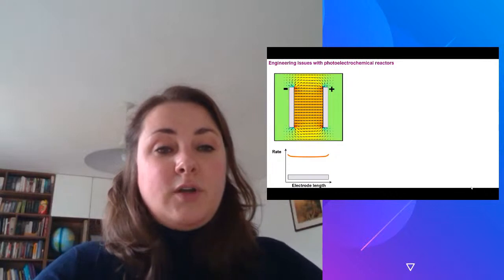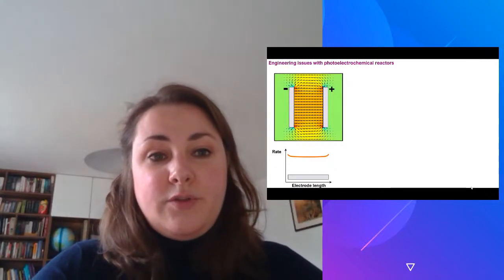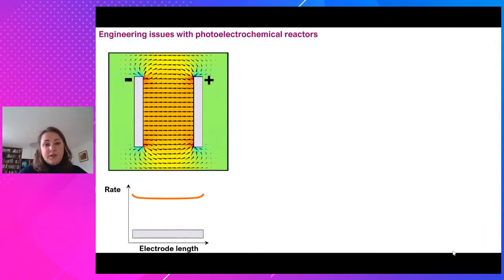So one of the main issues is to do with the symmetry of the electric field between what's usually a cathode, the negatively polarized electrode in an electrolyzer, and the positively polarized one. You've got hydrogen evolving at your cathode, oxygen evolving at the anode. Now, in a standard electrolyzer, the electroactive surfaces at which the reactions happen face each other, so they're completely parallel to each other, which means that the electric field is uniform, except at the very edges.